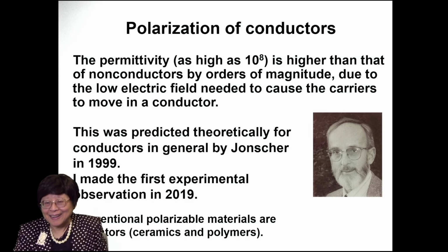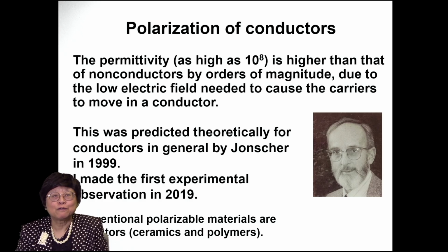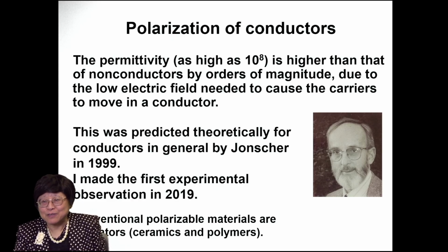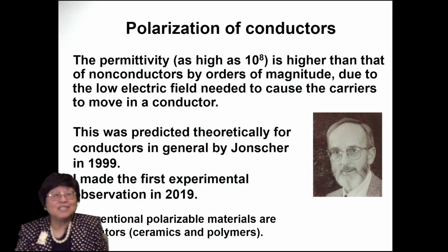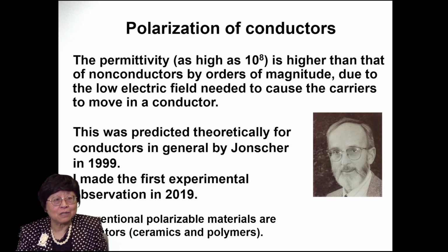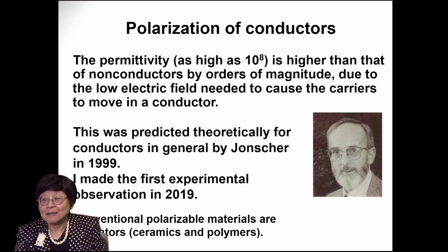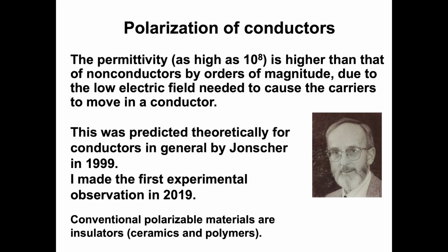However, recently we made a very revolutionary step, to extend the permittivity or capacitance concept from insulators to conductors. Sounds crazy, but actually, after a lot of literature research, we found that Jonscher, back in 1999, predicted that in high conductivity materials, by theory, the permittivity can be as high as 10 to the 8. Unfortunately, he passed away 6 years after the prediction. And 20 years after the prediction, that is 2019, I made the first experimental observation of such huge permittivity in conductors, such as metals and carbons.